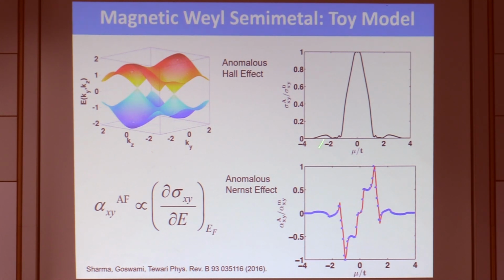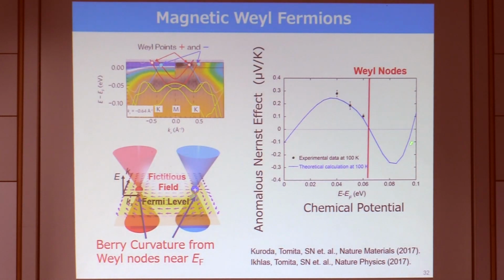On the other hand, the anomalous Nernst effect, which is given by the energy derivative based on the Mott relation, shows that there has to be a sign change and a large enhancement again near the Weyl point. And we investigated whether this is the case, and in fact, Arita-san's calculation indicated it is indeed the case for this material. First of all, this band calculation suggested the Weyl point near the chemical potential at the Fermi energy, and one can also tune the chemical potential by the manganese doping level. We systematically tuned the manganese doping level and found that it actually followed the theoretical curve.